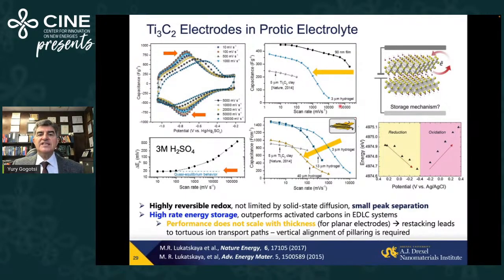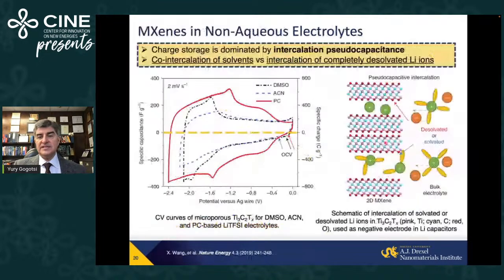So what it shows is that it's possible to have redox energy storage, high energy storage, at extremely high rate. We're not limited by the rate of the redox process. We're limited by transport. That's why when we go from thin film to thick electrodes, we lose somewhat in capacity, in charge storage. And it means that we need to design architecture in addition to having high rate redox materials. So electronic conductivity was really the limiting factor so far for other materials. That's why you cannot do the same charging with oxides, for example. And again, we know from X-ray absorption spectroscopy there is reversible oxidation and reduction of titanium atoms on the surface here.